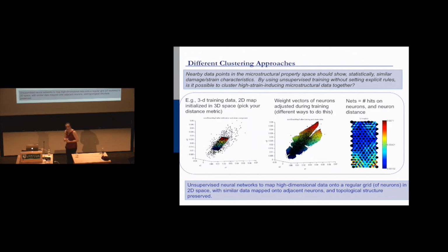What we like about it is that it's completely unbiased. We have none of our bias in there at all. And what's coming out is, when you do something called HPCA, or hierarchical principal component analysis, all that does is it takes the factors you would put in, Schmid factor, grain size, grain orientation, and combines them into fewer factors that are combinations of those, that it finds are important. And so we do our self-organized map not in terms of the individual microstructural factors, but actually in terms of these combined factors.